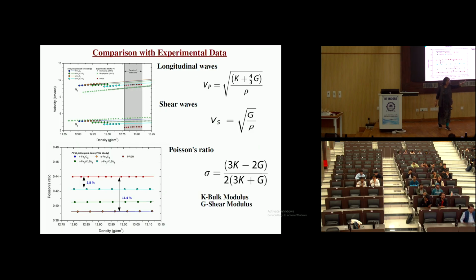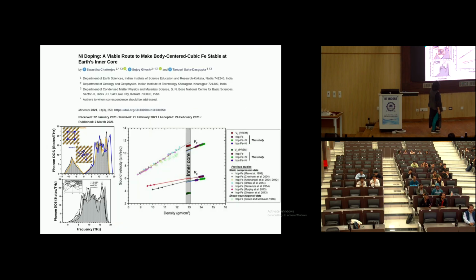We do find that if we consider this iron carbide with silicon, it is very close to the experimental data. But there is this catch that you have only 3 unknowns and you are trying to fit all different possibilities. I'll finish with only one other possibility. As you can see, Sujoy, who is a geologist, is one of the authors here. The previous one also had Sujoy. Here we asked how you can stabilize BCC iron at the Earth's core condition, and we found that if, in addition to iron, it has some nickel, then that can stabilize the BCC phase of the iron, and that can also explain the sound velocities Vp and Vs that I mentioned, as well as the density. So is it BCC iron with a bit of nickel in it, or is it really iron carbide with some silicon in it?